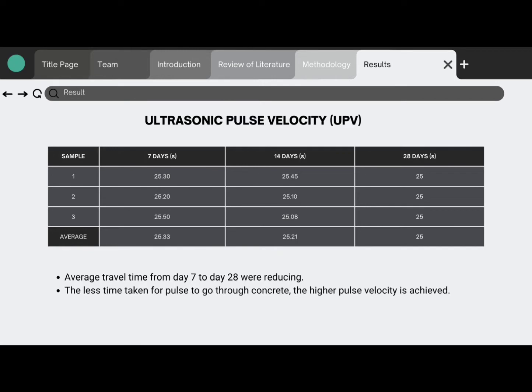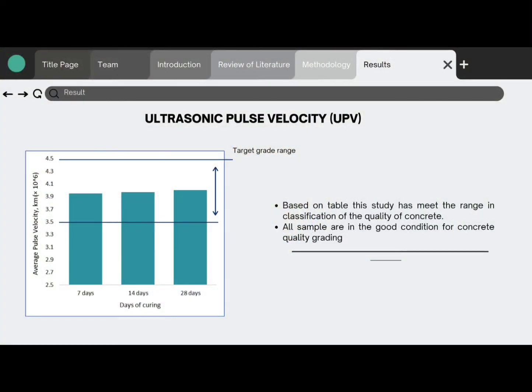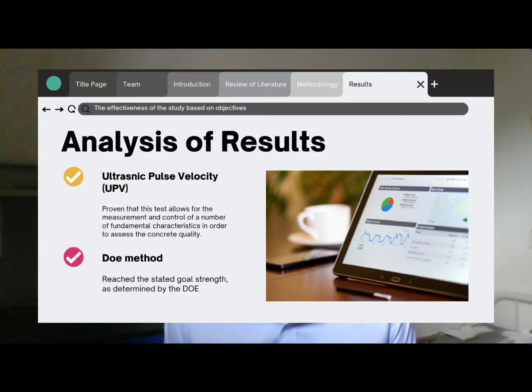Okay, next let's go to our second test result, which is ultrasonic pulse velocity, known as the UPV test. As we can see from the table, the average travel time from day 7 to day 28 is reducing. After we make a calculation of pulse velocity, we can conclude that the less time taken for the pulse to go through concrete, the higher the pulse velocity achieved. Clearly, from the graph, this study has met the target because the average pulse velocity for the 7, 14 and 28 days samples has been in the target range. All samples are in good condition for concrete quality grading, which is the target grade for 25 MPa concrete.